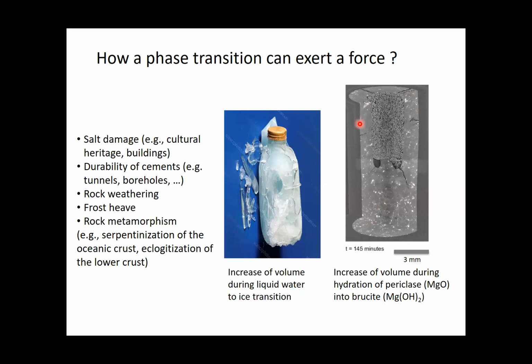So here I show you on the right side a movie. I will come back a bit later to the same movie. It's an experiment at in situ conditions where we start with a material which is in the middle here, which is located in a rock container. And this material is periclase, a magnesium oxide, which can become unstable under the addition of water and evolve into brucite, Mg(OH)2.